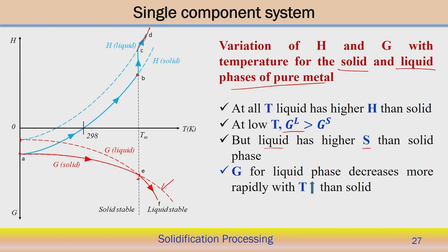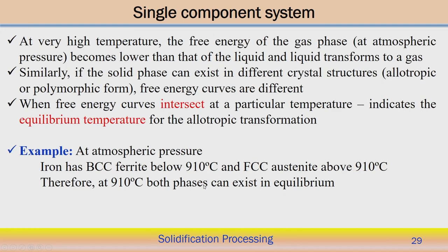So, this is the curve for the solid phase, G solid, and this is the curve for the G liquid phase, but here definitely it will follow the liquid phase curve. So, it is lower than the G solid phase curve. That means the Gibbs free energy is further decreasing. Once it crosses the melting point temperature, that means the solid has transformed to the liquid, it becomes more stable, and that is indicated by the lower Gibbs free energy curve. So, overall we can see for a single component system